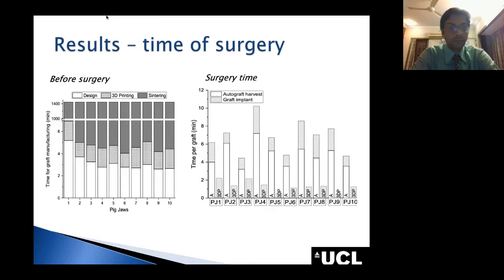And then moving on to the surgical time, we can see that the autograft took around 5 or 6 minutes, also because, of course, the surgeon had to harvest the secondary graft from the donor site of the pig jaw and reshape it. And the graft implant took around 2 or 3 minutes, and that was due to the reshaping part. The 3D printed graft took sometimes even less than a minute because only the screw needed to be placed.